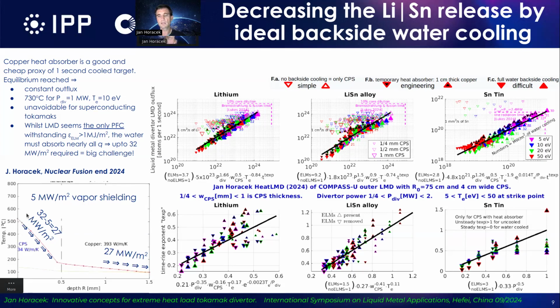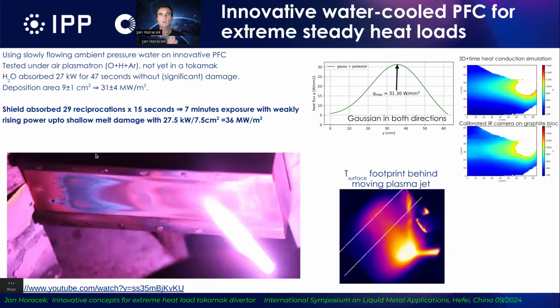So it means that we are getting to the limit of the water cooling, because a normal ITER-like divertor, which I showed in the beginning of my talk, cannot extract so much heat power flux density. So it's a big challenge. And that's why we started a project which is called Innovative Water-Cooled Plasma Facing Components for Extreme Steady Loads, which is, I hope, not useful only for liquid metals, but also for other systems, where we did it purely experimentally. So we developed a new structure based on copper, where there is water flowing in it and extracts the heat very efficiently.